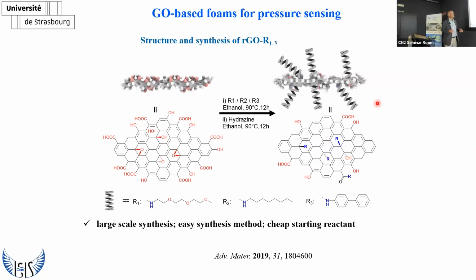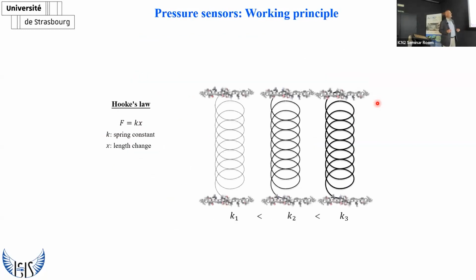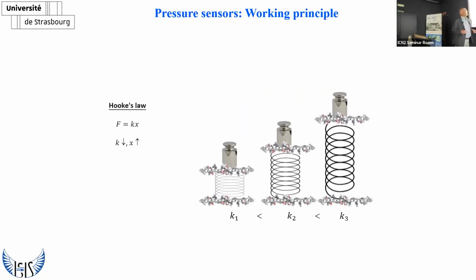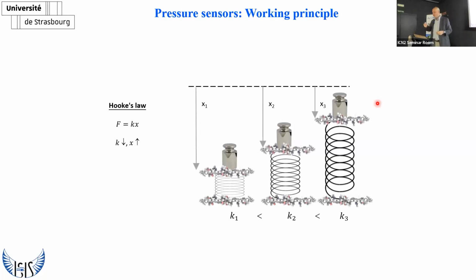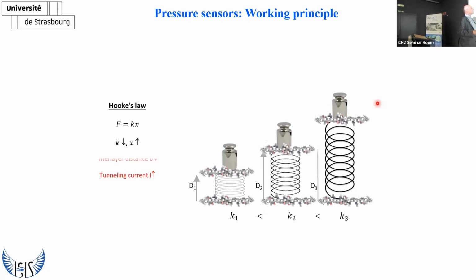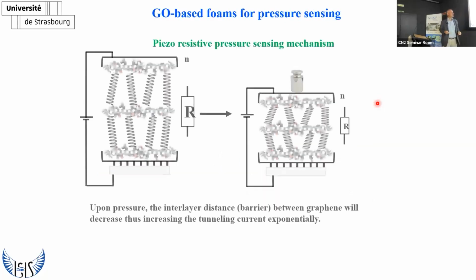And so we make this kind of layered discs. My idea was that I wanted to exploit Hooke's law on the nanoscale. By changing the chemical composition of the backbone, I would change the force constant of my spring, in such a way that when I apply a weight on top of it, the most flexible one will compress more. And compress more means what? It means that the distance will be tinier, and so the tunneling current change would be higher.